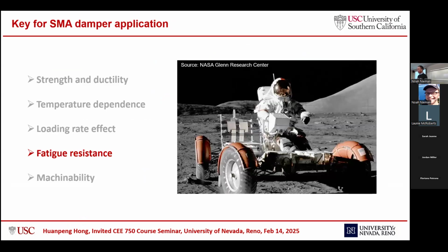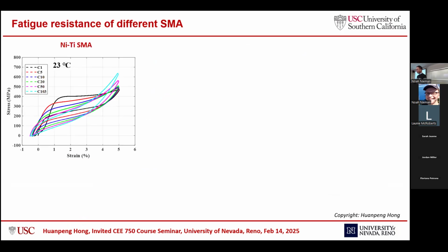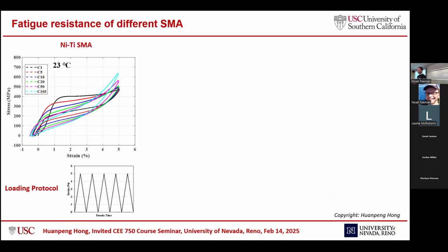So next is the fatigue resistance. So here is what we did. The fatigue resistance is important because for vibration dampers, bridges, earthquake engineering, or dampers in automobiles or space rovers, constant cyclic loading will cause premature failure or function degradation of this material. Here, we used 5% constant strain loading, just loading, unloading, loading, unloading until the material fractures.